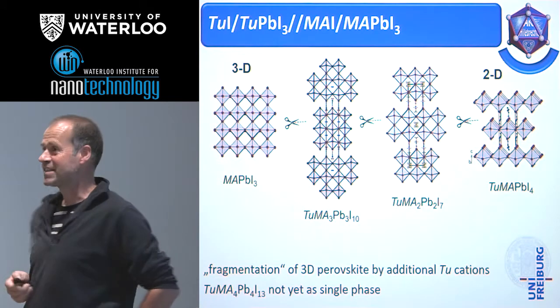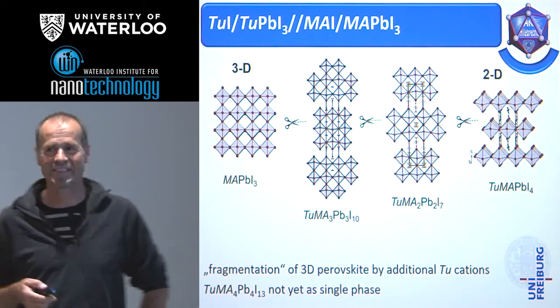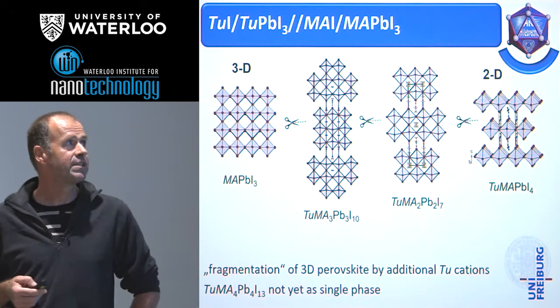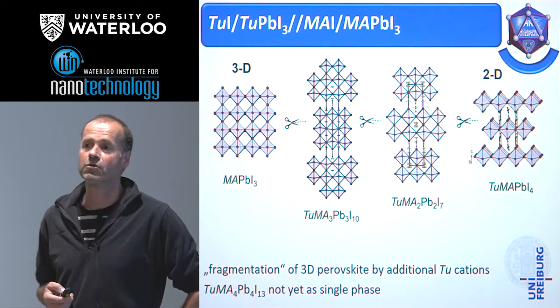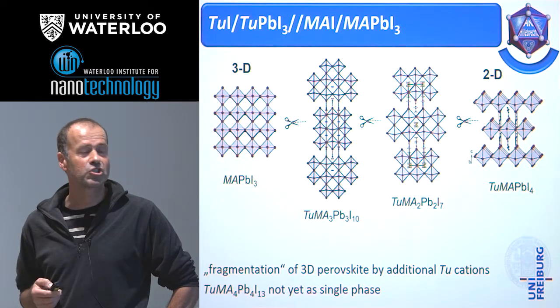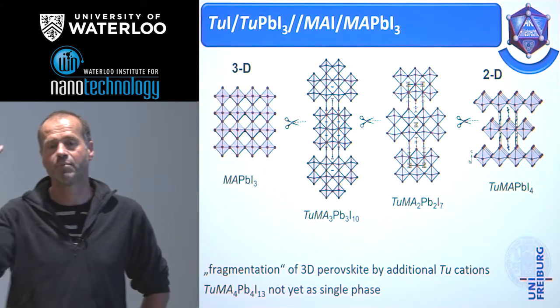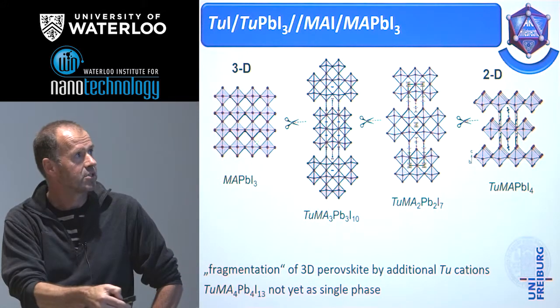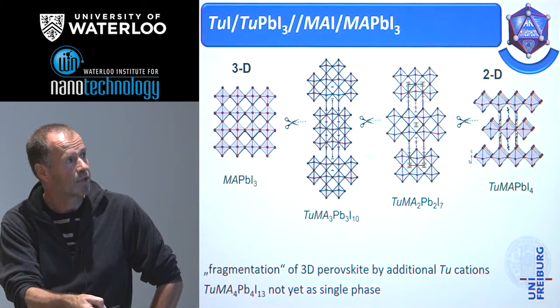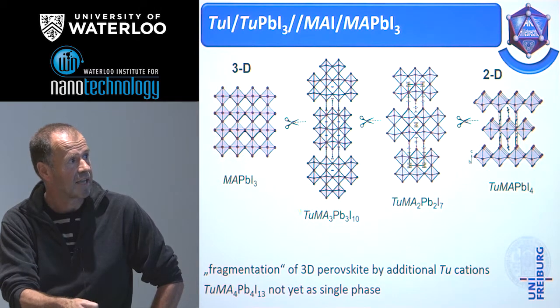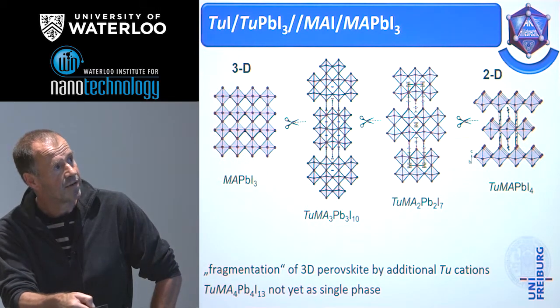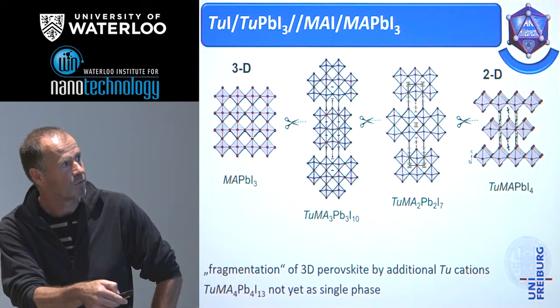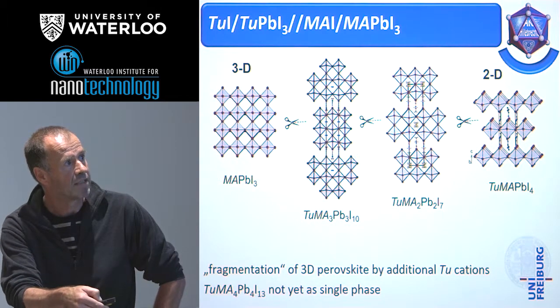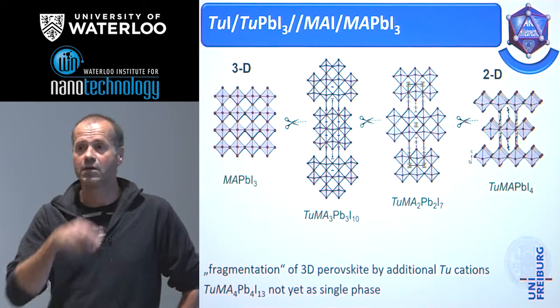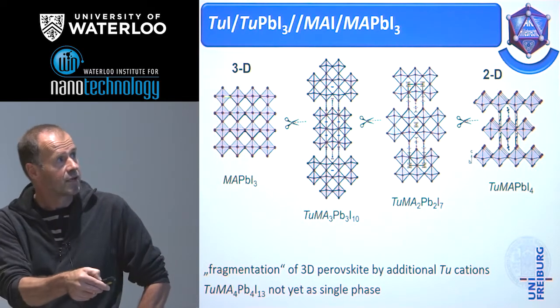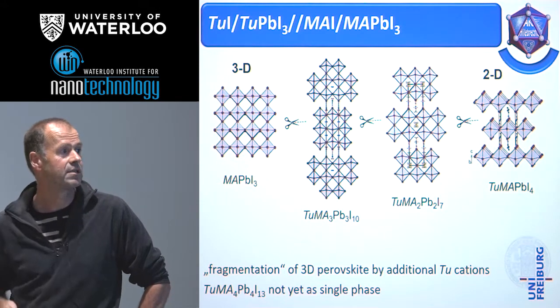And the last story is the most interesting story. You should always keep your interesting things to the end. By introducing this protonated thiourea into this chemistry, we could show that indeed the idea to separate the three-dimensional structure of the original perovskite by the special demands of the coordination of the second cation leads to a well-defined series of different structures. I've shown it with these scissors that you may cut the three-dimensional structures in appropriate layers, and we could characterize all of them. That means we have a continuous transition from the three-dimensional to the two-dimensional structure.